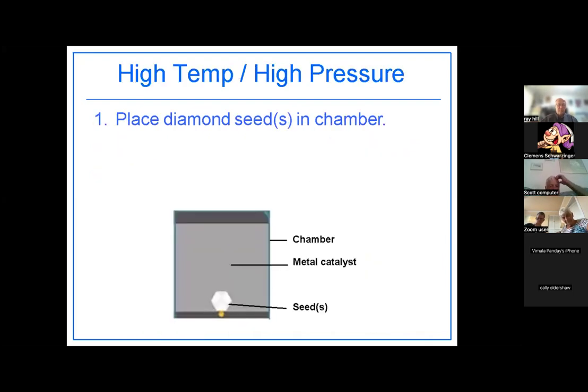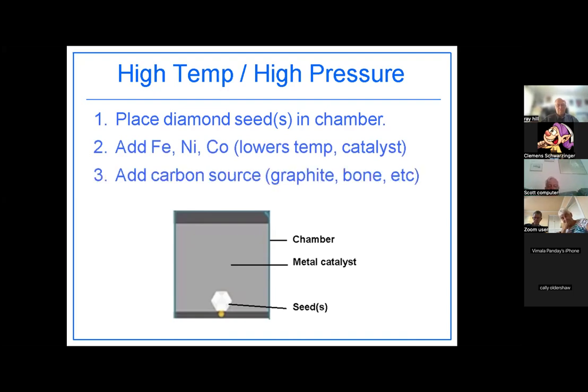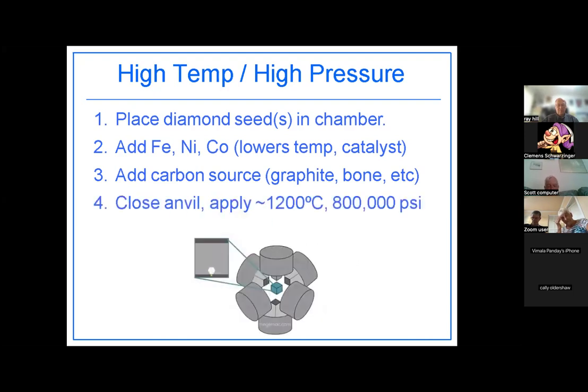Now we take a look at the high temperature, high pressure. What happens? You have your seed diamond in a chamber that's filled with a metal catalyst, usually nickel, iron, possibly cobalt. And now you're just going to squeeze the living stuffing out of everything as you heat it up. And your carbon source in your seed could be anything containing carbon. And this is where, if you want to take your cremated remains of dear Aunt Agnes and turn it into a diamond, this is how that diamond would be created. But anything that contains carbon is fair game.